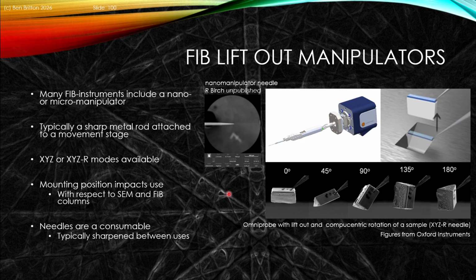To do a lot of these processes and to enable us to do lift-out, we could use effectively a micromanipulator needle. And so this needle effectively is located on like an XYZ or an XYZR stage. This is one such example. And in this process, we effectively have the sharp needle, and we can stick the surface of our object through welding with the gas injection system, and we can do that to enable us to put the needle in the surface of the sample, and then we can move the needle upwards or move the sample downwards and liberate the object once it's welded. If we've got an R rotation stage, such as on one of the Omniprobe systems, you can effectively rotate the object, and this can enable you to access and look at how the shape of the object is in 3 dimensions.